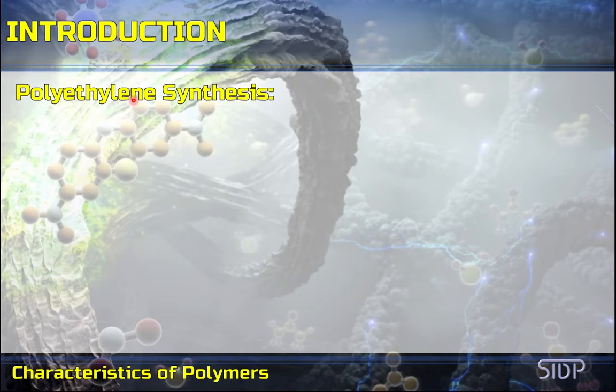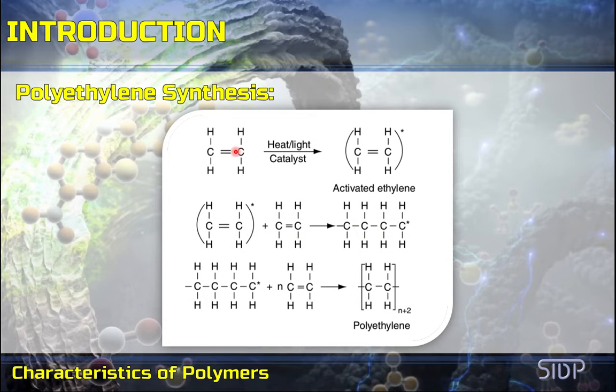For example, ethylene, the prototype monomer molecule, is very reactive because it has a double bond. Under the influence of heat, light, or chemical agents, this bond becomes so activated that a chain reaction of self-addition of ethylene molecules is generated, resulting in the production of a high molecular weight material, almost identical in chemical composition to ethylene, known as polyethylene, the polymer of ethylene.